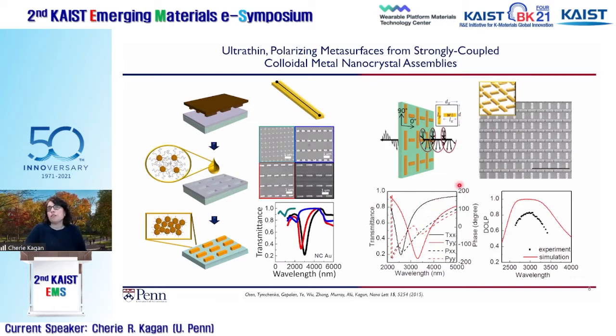And so we did an experiment where we created linearly polarized light, and we bought a commercial quarter wave plate to create circularly polarized light. Now the challenge is that that commercial plate, of course, was millimeters thick. It cost $2,000. We waited 2 months to get it, and it only operated over a narrow spectral range. But it allowed us to do our experiment and show that if we send in circularly polarized light, and the surface that we fabricated operates as a quarter wave plate, then the transmitted light should be linearly polarized.